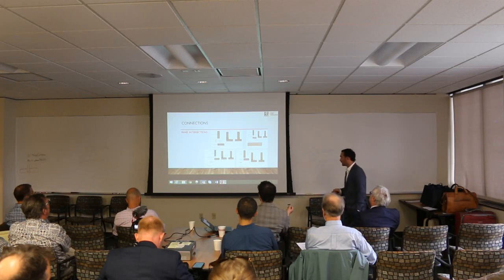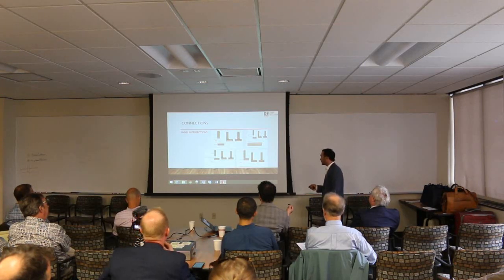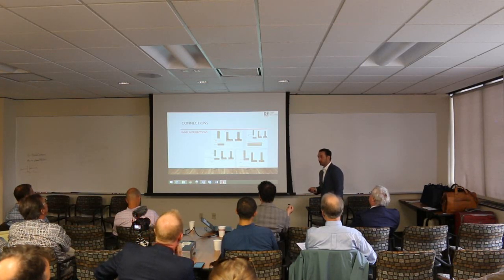Some of the things to think about there, if you're a structural guy, is when you're putting these connections together, you can't be screwing into the end grain of some of the layers. You need to be conscious of what layers you're screwing into.